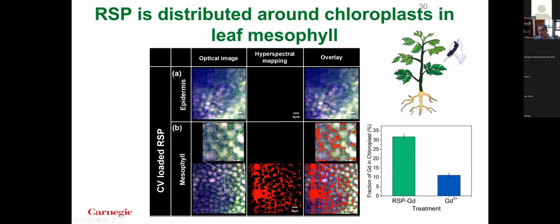You know, it's hard to know for sure with this hyperspectral imaging. So what we did is we extracted a bunch of chloroplasts and we looked at how much of the gadolinium in the particles was associated with chloroplasts. And it turned out that about 30% of the gadolinium that we applied ends up being associated with the chloroplasts when we have it in our star polymers. If you just put free gadolinium on, a lot less is associated with the chloroplasts. So we're pretty sure that this stuff is going through, it's getting into mesophyll, it's getting through cell walls and cell membranes and associating itself with chloroplasts, which again is a good thing.